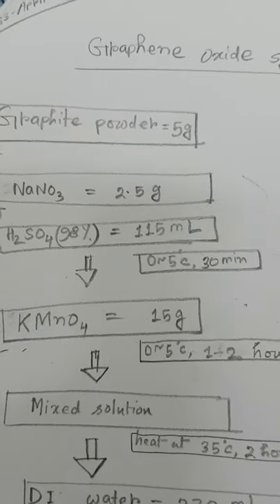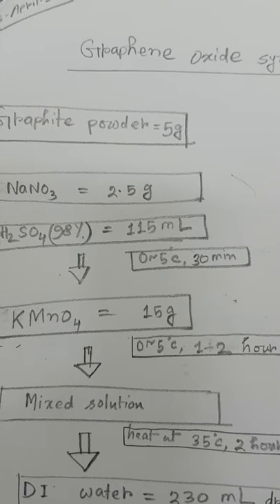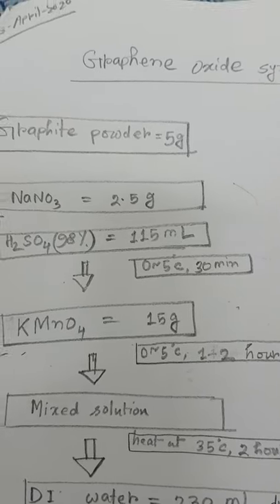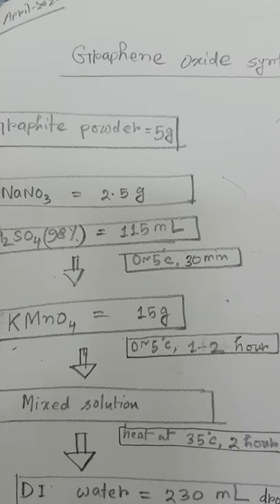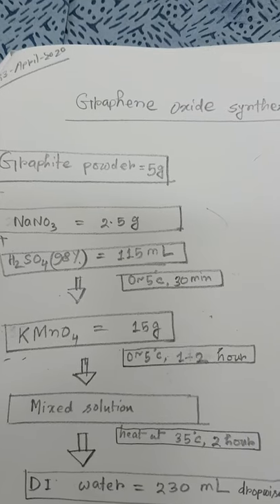15 grams was added drop by drop very slowly. The temperature remained constant at less than 5 degrees and the reaction time was 1 to 2 hours.